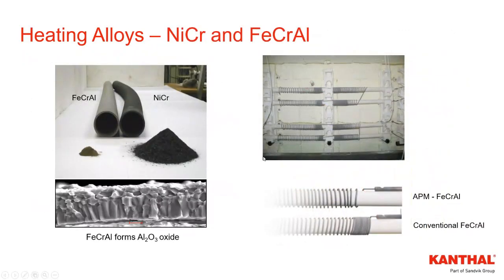And then we have here some pictures showing the performance of the oxide, and then some basic strength of the materials, and comparisons. The more the oxide that spalls off the alloy, it's oxide thickness and spallation. There's a difference between an iron chrome aluminum alloy and nickel chrome.